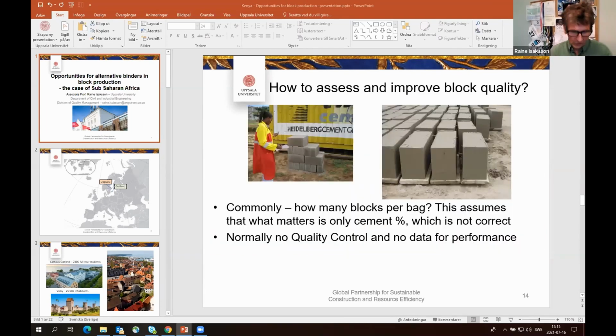Normally, what is measured is how many blocks I get out of a bag of cement. 36 blocks out of a bag of cement is reasonable. 35 is even better. That means about 5% cement. These blocks are weighing about 30 kilos. But this is the same measure as for productivity, and it assumes that the only thing that matters is the percentage of cement, which is not correct.